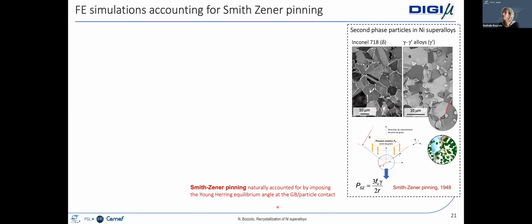Actually, in the full field finite element framework, the Smith-Zener pinning is naturally accounted for simply by imposing the contact angles of the boundary with the surface of the particle. I mean by this, we do not have in the full field models to add any additional such pinning force. The pinning effect is naturally taken into account simply by the capillarity interactions between the boundaries and the second phase particles.